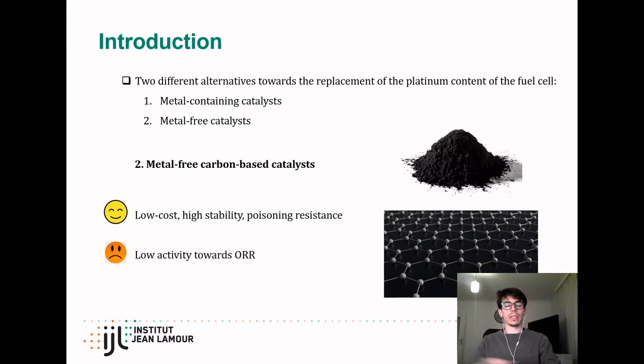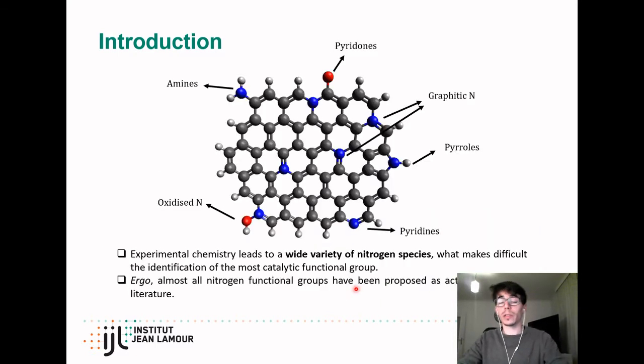In order to increase this catalytic activity, the introduction of heteroatoms or even defects is mandatory with the aim of disturbing the electronic density of the carbon material, leading to the chemisorption and reduction of the oxygen molecules. This is especially important when using nitrogen-doped carbon materials, which have proven to be capable of reducing oxygen molecules very efficiently. But in experimental chemistry, when we prepare a carbon material, this carbon often consists of a wide variety of nitrogen species, which makes it almost impossible to identify which of these nitrogen functional groups are the truly active sites towards the oxygen reduction reaction.